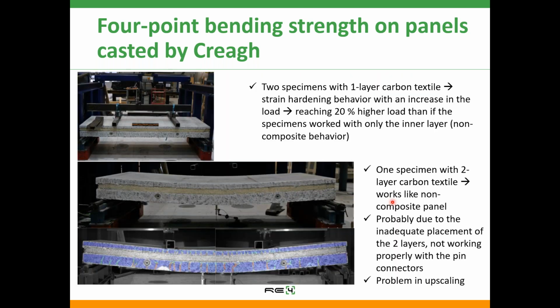With these elements in 4-point bending strength, once again we wanted to confirm that it was the right choice to use 1 layer of carbon fiber in the outer layer, because one of these 3 panels had 2 layers of carbon fiber in the outer layer. The results from this 4-point bending strength test, surveyed by digital image correlation, were that 1 layer proved to be the best one.